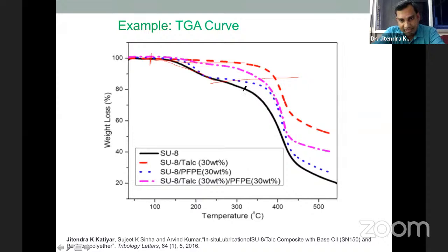This is the basic temperature where decrement starts, and this is the temperature up to which you can keep your sample stable. This temperature is very, very important for analysis. What we observe in the case of SU8 is that after adding the filler, we can increase this temperature a little bit, with a difference of 120 degrees centigrade. That analysis is very important.